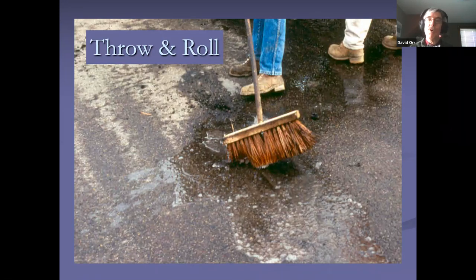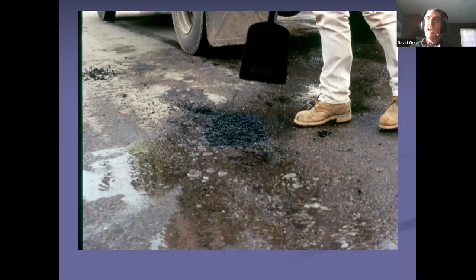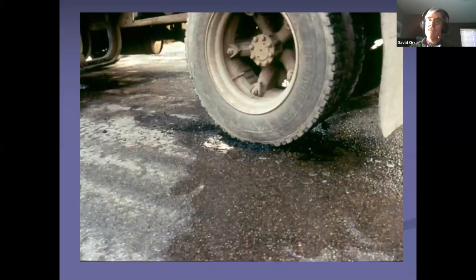Now, you can sweep the whole lot if you've got a broom, but the modern proprietary mixes that are made with polymers are going to work even in the water. That's what they're designed to work in. The key, though, is you've got to have pressure. You've got to compact them to activate that polymer. The back end of your truck tire actually does a pretty good job of that.